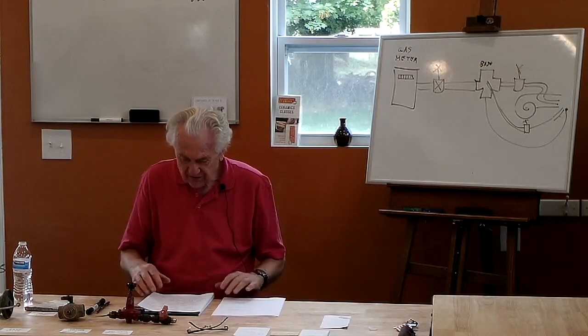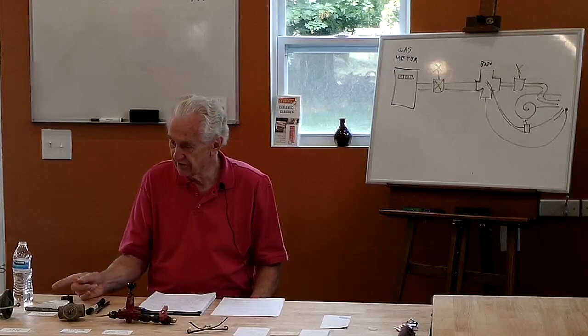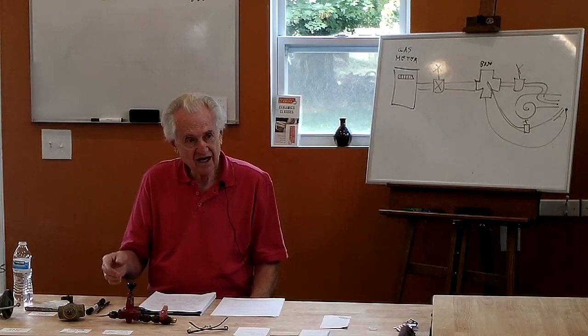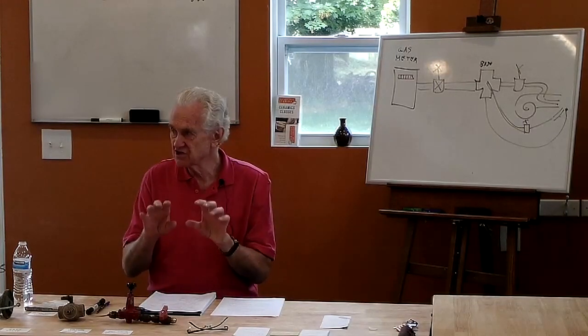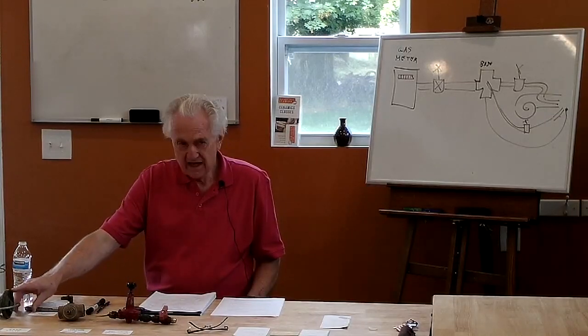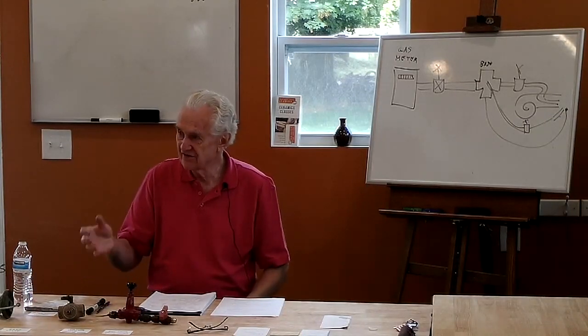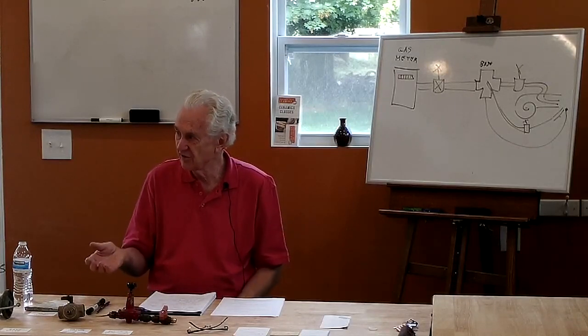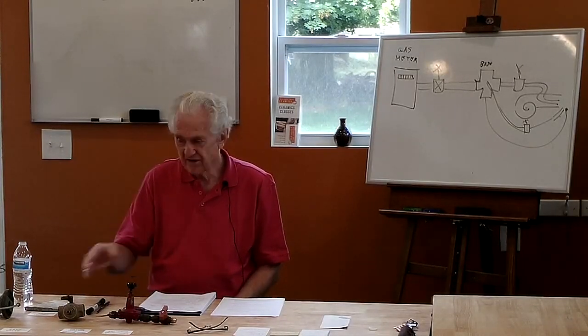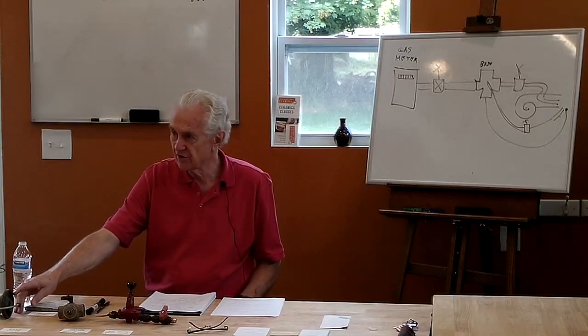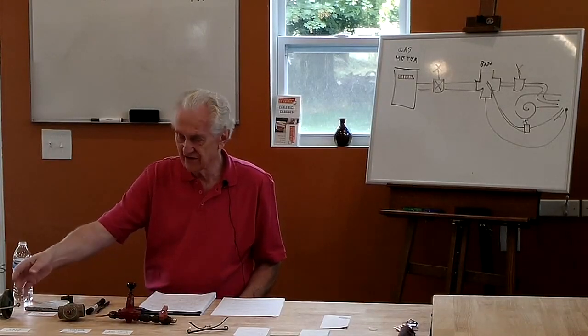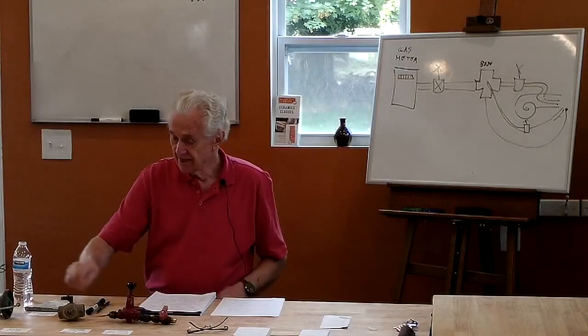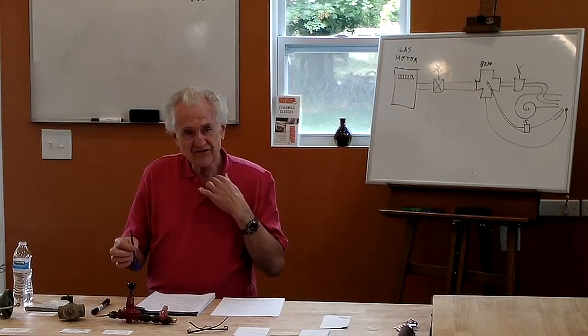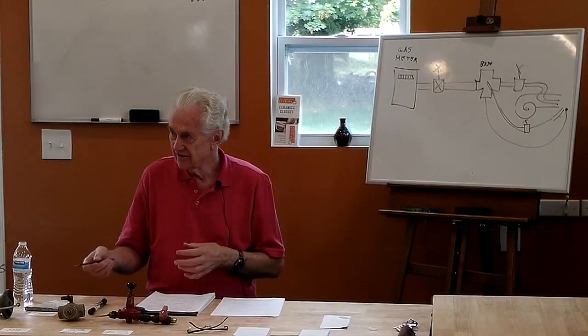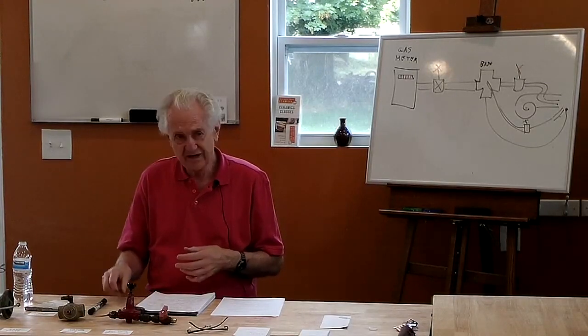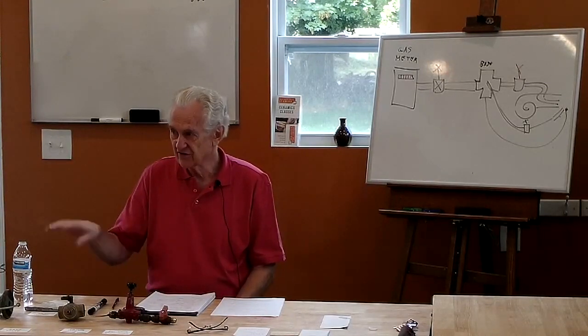And another important design feature is that with Venturi burners, I need to have inlets into the kiln for additional air. The air that the burner pulls in by itself is not enough to get complete combustion of all the gas. This air, by the way, that's coming into the burner is called primary air. It's the air that's mixing immediately with the fuel. But that's not enough air to completely burn all the fuel. So I need additional air.